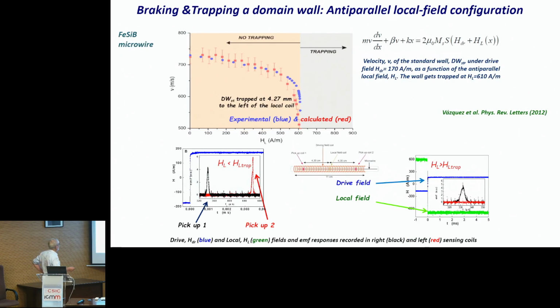Years ago, we were able to control the velocity of this domain wall just by playing with the value of the local field in the center of the solenoid. So we are able to reduce the velocity and to stop the domain wall in a particular place. You see the experimental and calculated points. This is important because we can control not only the velocity of the domain wall, from 1 kilometer per second to very small values, but also we can stop the domain wall in a particular position.